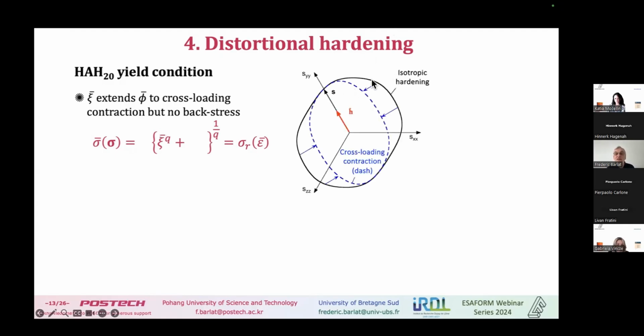And this would be in a pi plane. Again, it would be the solid line, if it's normalized, and it would always be this solid black line here. But actually, this is the yield or the effective stress, but the effective stress is actually this chi bar, which is extended to allow some cross effect. So if you look at the figure, the dashed line would be some kind of contraction that occurs during loading in this direction.